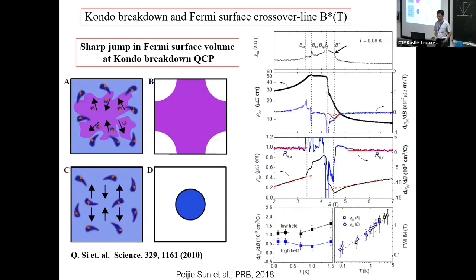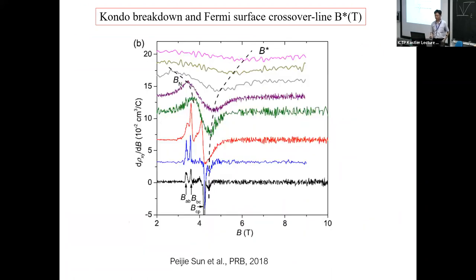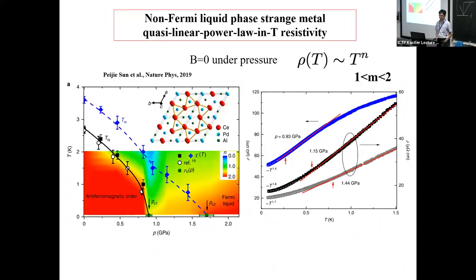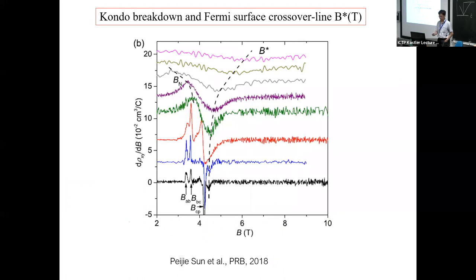And about the Kondo breakdown transition, from this Hall coefficient measurement, this material shows a jump between the small Fermi surface at low field and the large Fermi surface at high field. So it clearly indicates a very sharp jump transition between the two sides of Fermi surface, which indicates that if there's a Kondo effect, which I'll talk about in a moment, and the f electron participates in the Fermi surface, the Fermi surface will get enlarged. But if Kondo disappears, then the Fermi surface is small. So it's directly indicating whether or not the Kondo effect plays a role here. So there's a transition near the end of the paramagnetic phase that is a Kondo breakdown transition. And we could define this crossover scale, B star.